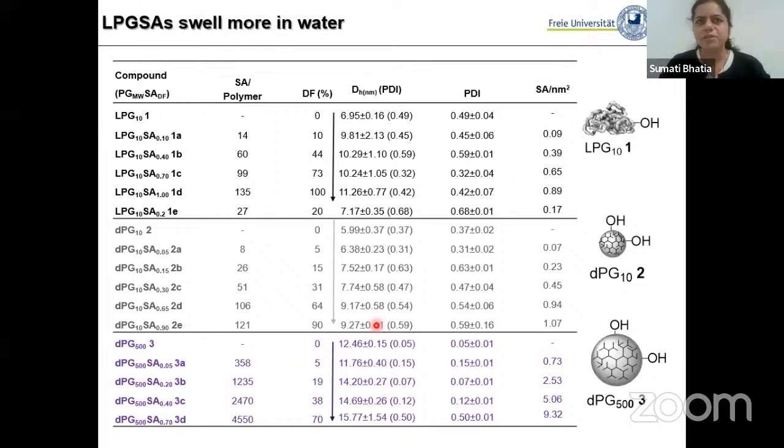And if we look at the hydrodynamic diameter, one can obtain it from dynamic light scattering, which is a very common technique to determine the size of different particles when they are dispersed in water or in any other solvent. Because all the particles dispersed in a solvent have Brownian motion, if you can track their speed, you can determine the diffusion coefficient. The machine can then tell you, by applying the Stokes-Einstein equation, what the hydrodynamic diameter of these particles is.